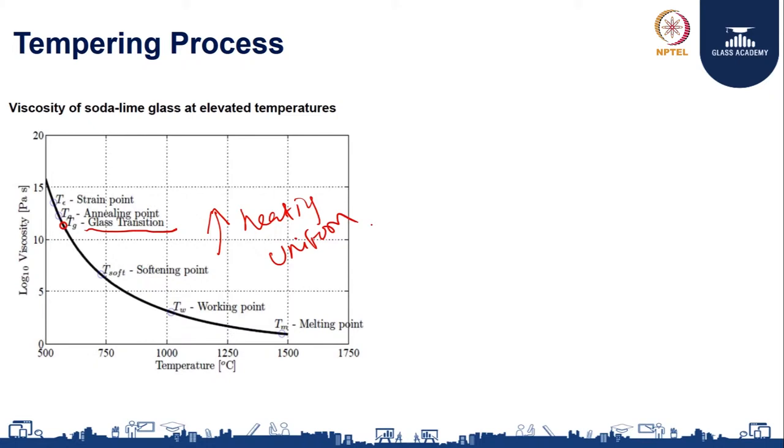So, the key point is that for soda lime glass, which we generally call float glass, the glass transition temperature will be close to 580 degrees Celsius, and we normally measure the air temperature in the tempering machines. Normal air temperatures will be around 650 degrees Celsius, so that it ensures the glass temperature is reached. After the glass comes out of the heating zone, it is measured using a pyrometer to understand the heat